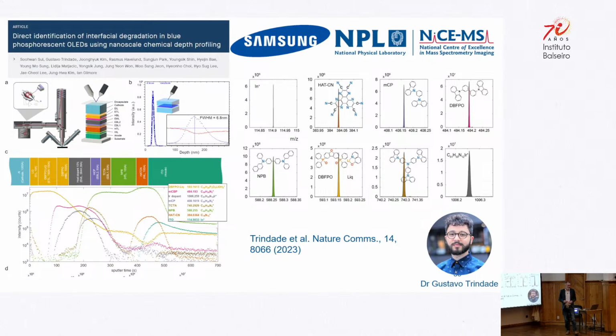The blue LED, the blue color, is the hardest to make stable. And this has still been a big challenge in the OLED industry. And you often see papers in Nature Communications about new advances to improve the lifetime. So we worked with Samsung to see if we could find what was causing the problem. Why were these devices failing? So this is an OrbiSIMS depth profile through one of these devices. Every single pixel, every dot you see here is a rich mass spectrum. So we're getting all of that molecular information from less than 1 nanometer of material.